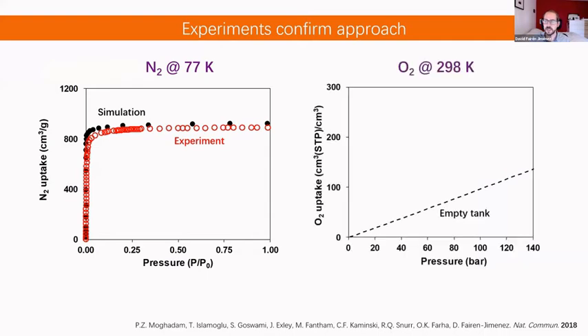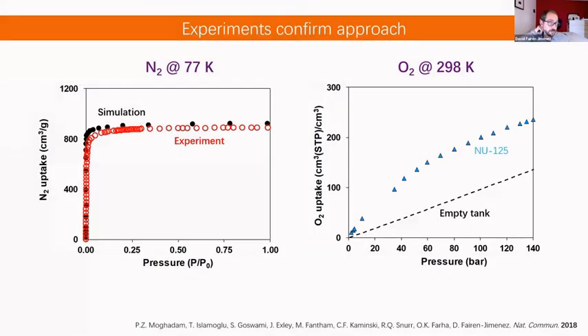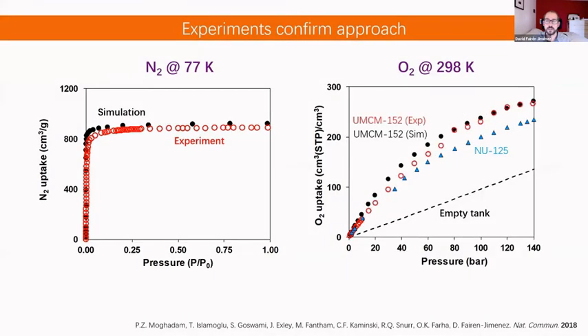And yes, it works. Simulations, because as soon as we compare with experiments, we have a very good match. And if we go for the application that we were looking at here, oxygen storage, this is volumetric capacity. This is the empty tank, just compressing the oxygen inside the tank. That was the best material published in the literature before this study. This is the simulations for the best material. That was a 20% improvement. And this is our experimental data, basically confirming that at high pressure, we are able to match the molecular simulation. So really, really beautiful results.